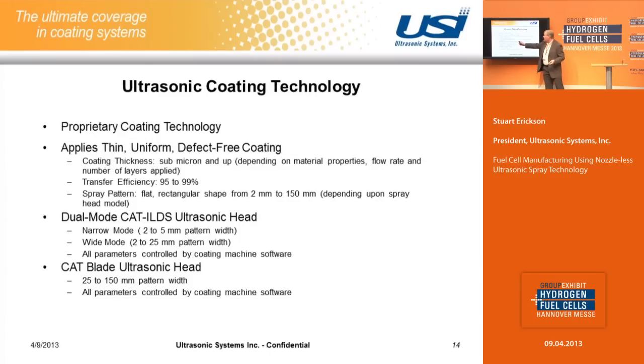And we have another head that's a much narrower head, but that operates in two modes. It can produce a flat spray pattern up to 25 millimeters wide, but it also can produce a focused spray pattern down to about 2 millimeters in diameter. So it can actually do a circular focus pattern and a wide pattern with the same head, and all the parameters, including going back and forth between the spray patterns, are controlled by the machine.